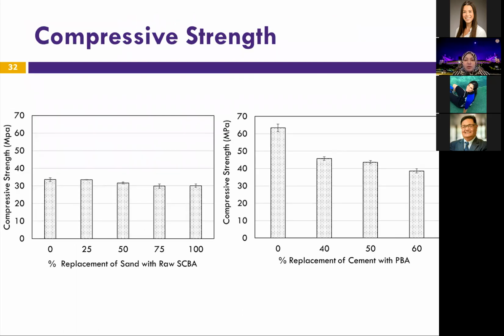Okay, this slide shows the compressive strengths of both the raw bagasse ash and the processed bagasse ash. The use of bagasse ash as a sand replacement, as you can see here, had minimal effect on the compressive strengths. In contrast, increasing the replacement of cement with the processed bagasse ash did reduce the compressive strength. Although we have a lot of amorphous silicon dioxide in the processed bagasse ash, which indicates that there is a high potential for pozzolanic activity, the observed decrease in compressive strength can be attributed to the strength activity index. We saw that it was more than 75%, but it's lower than 100. So still, it's not as high as can be.